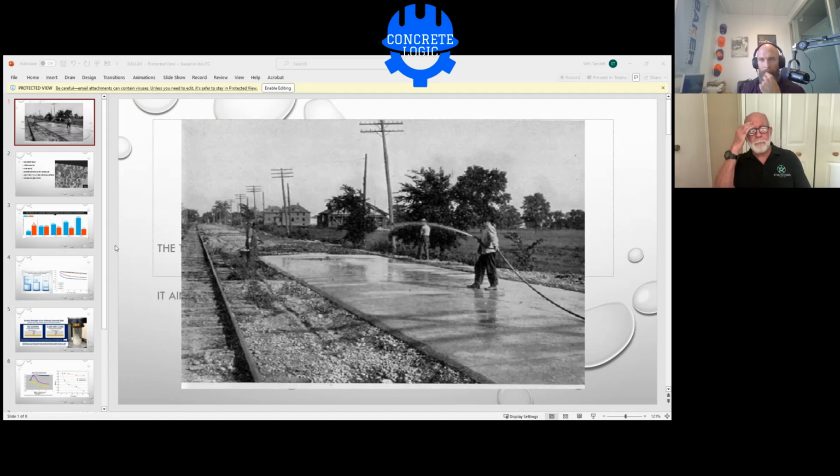But then they found that if you grind cement finer, it would produce a much faster set of concrete and would cure faster, but also produce more heat. And that was not ever adjusted for. And at first, it didn't matter because the grinding wasn't so fine that it created issues that were noticeable as long as you used a water cure.